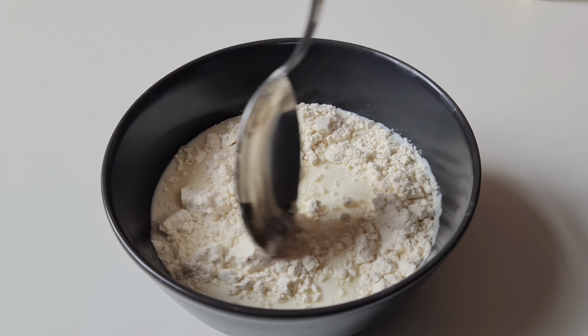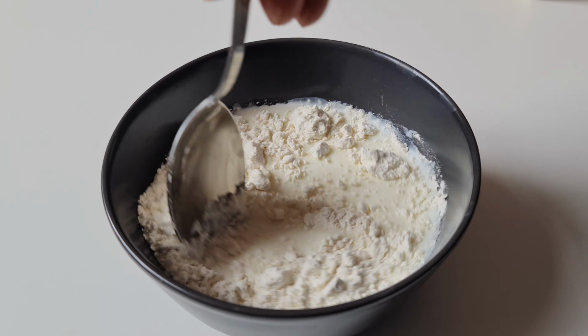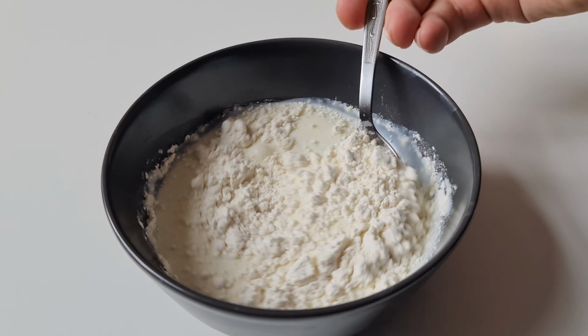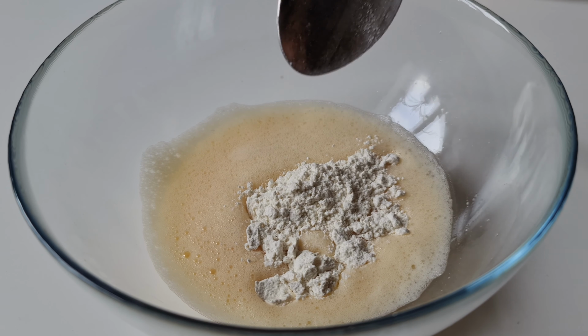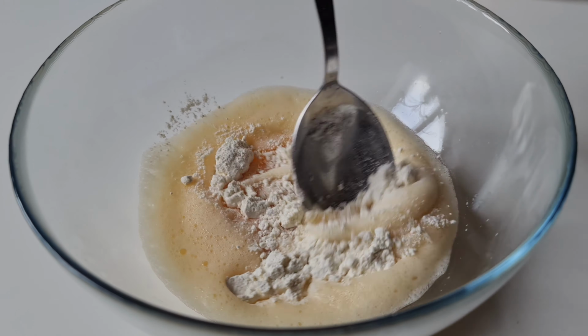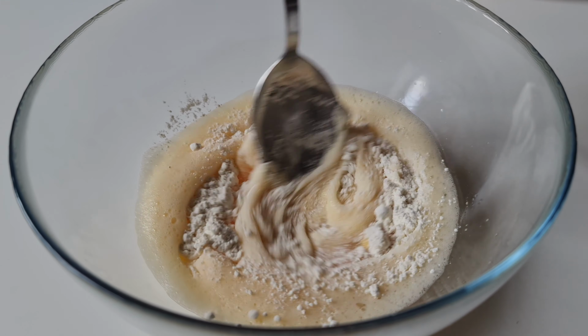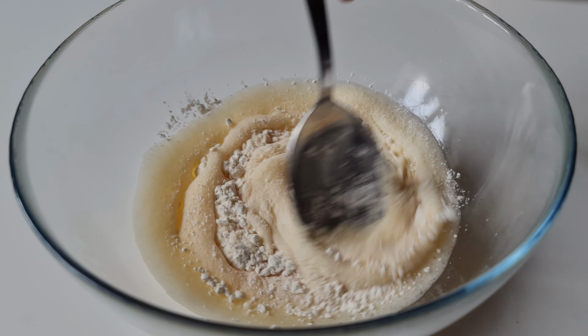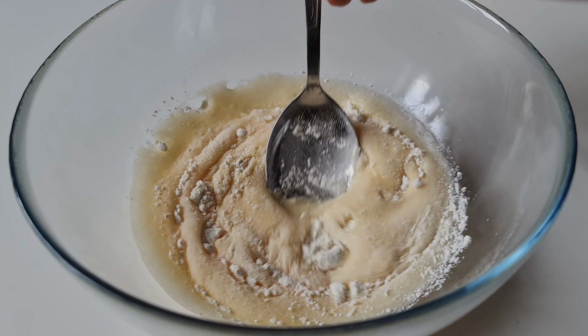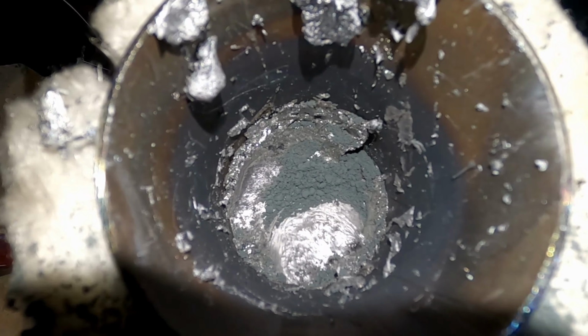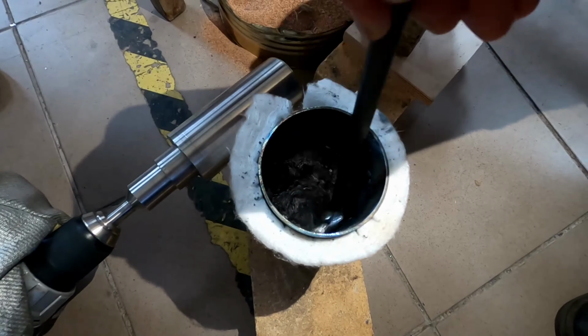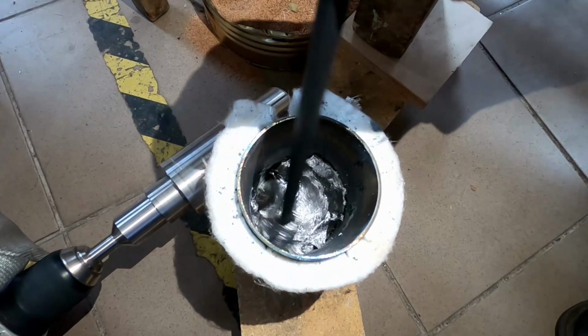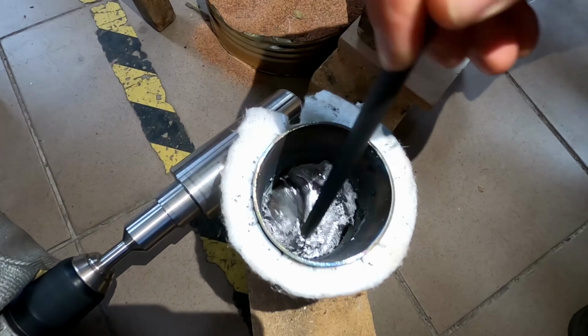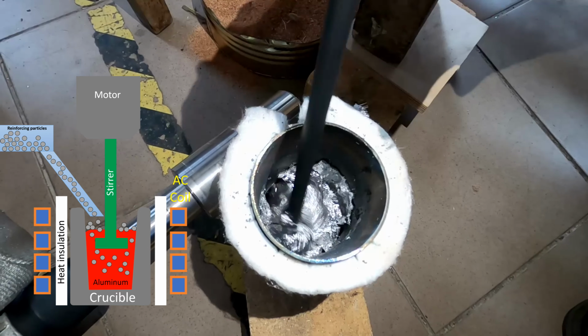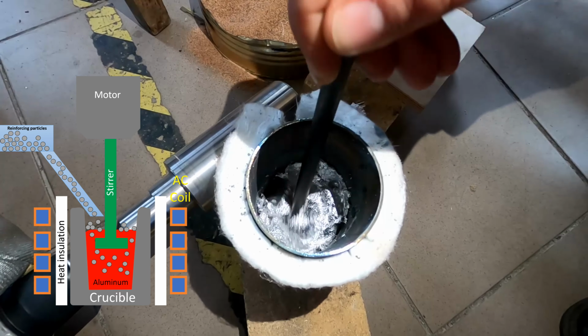If you pour flour directly into milk, it clumps together. You can divide the clumps by mixing, but it takes time. It is way easier to in-mix flour in a more viscous medium, such as eggs, or preferably an egg-flour combination. The same idea is used with semi-solid aluminum mixture, which can still be stirred, and the increased viscosity effect is exploited before casting the metal. This process is also called stir casting.